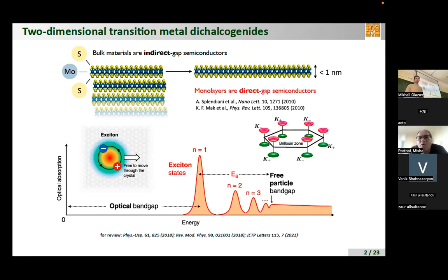Because we know that the dielectric constant enters quite prominently. Yes, so what people know for sure is that the main contribution to inhomogeneous broadening in this system is related to the so-called dielectric disorder. Just because of fluctuations of these hBN layers, you have fluctuations of the Rytova-Keldysh potential. Yeah, it induces a kind of inhomogeneous broadening. It is more or less established, I believe, both experimentally and theoretically.